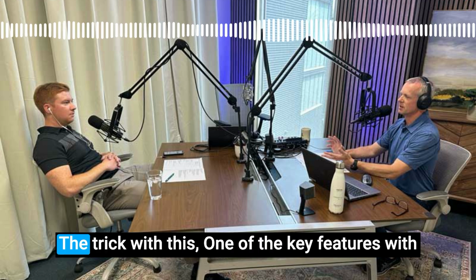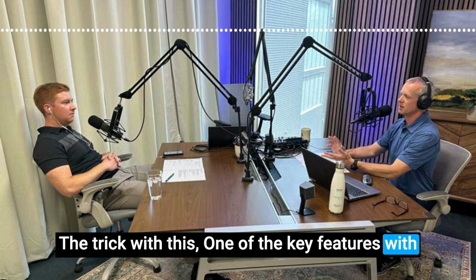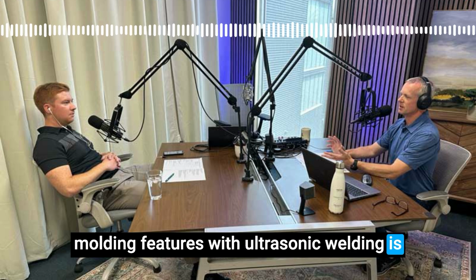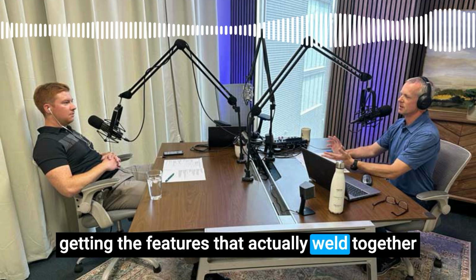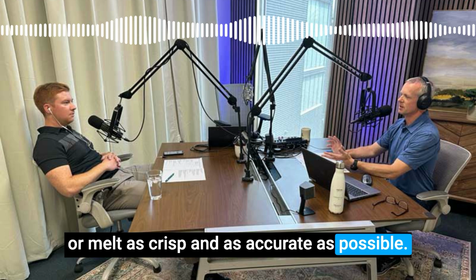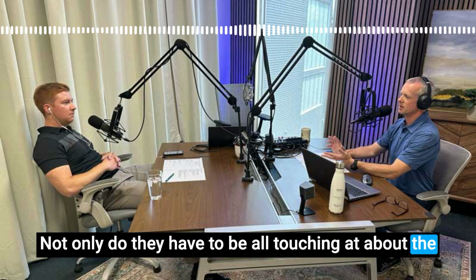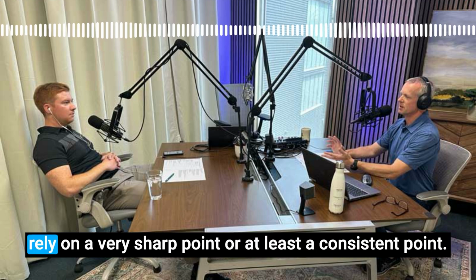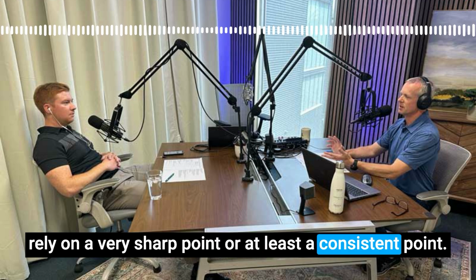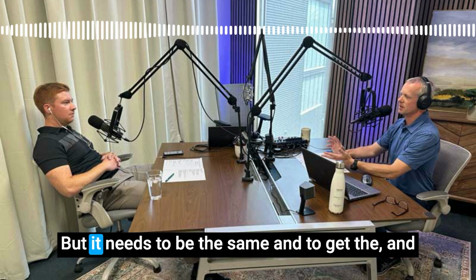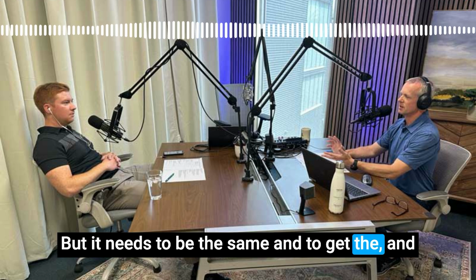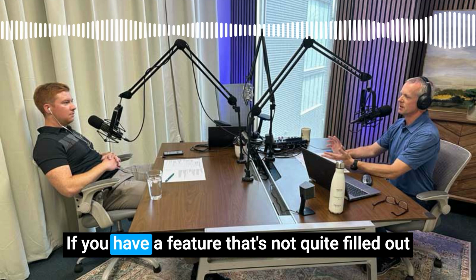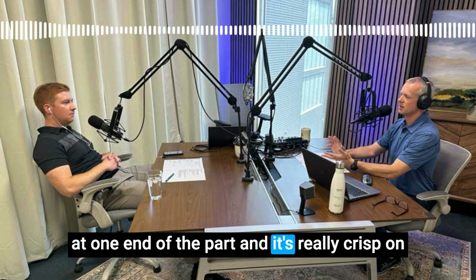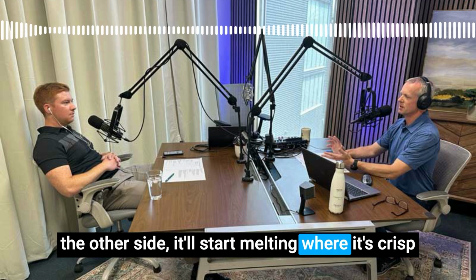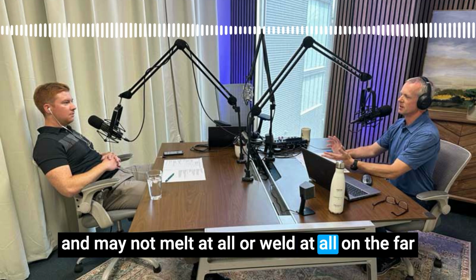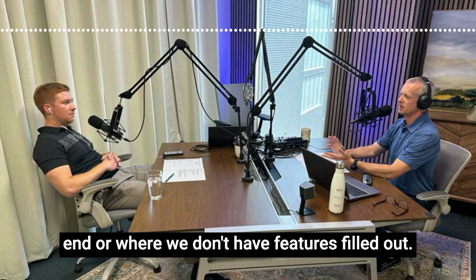It's really quite quick. One of the key features with molding features for ultrasonic welding is getting the features that actually weld together or melt as crisp and as accurate as possible. Not only do they have to be all touching at about the same time when they start welding, but a lot of those rely on a very sharp point or at least a consistent point. There's some going to more of a rounded point, but it needs to be the same to get an even melt all the way around that perimeter. If you have a feature that's not quite filled out at one end of the part and it's really crisp on the other side, it'll start melting where it's crisp and may not melt or weld at all on the far end, where we don't have features filled out.